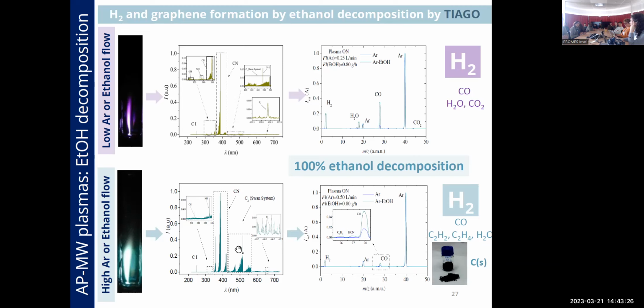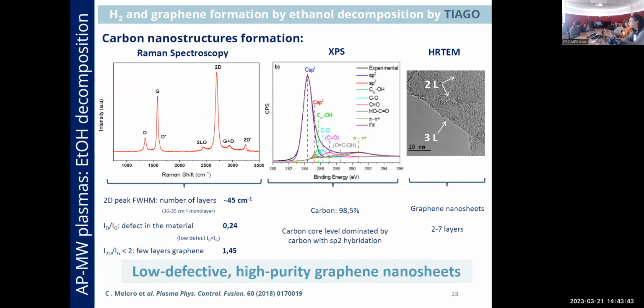This gives us an idea of how the ethanol is decomposed, but how is the graphene or graphene nanocomposite formed? So let's analyze our material. Once again, we analyze the material by Raman spectroscopy, XPS, and HRTEM. The Raman spectrum is quite similar to the one that I showed you previously. The most important difference is the intensity of the band. Remember that the 2D and G bands are related to the formation of graphene, and the thinner and more intense this one is, the better. So in this case, we are obtaining low defective and high purity graphene nanosheets.